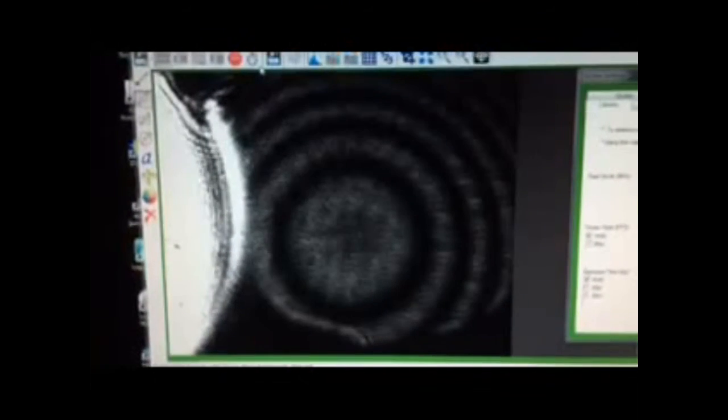Here you can see the fringes unresolved. They get bright, blend together, and shift in position. We believe many fringes passed during this period due to the discrete mode hopping of the laser diode which is why our fringe count was so low. If we had a source with a continuous wavelength shift, we are confident we would be able to count all the passing fringes and our experiment would produce an accurate index.